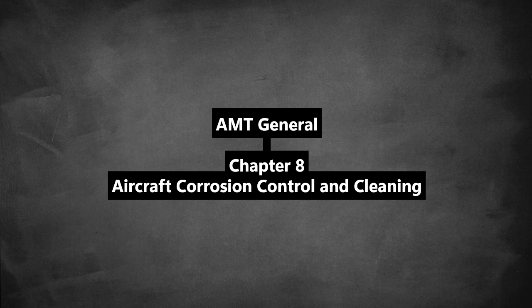Wet wash, dry wash. Wet wash uses water, usually with alkaline or emulsion cleaners sprayed or mopped on, then rinsed off. Good for oil, grease, general dirt. Dry wash uses minimal liquid, applied and wiped off with cloths or mops. Good for light dust or film when liquids aren't desirable. Polishing restores luster and removes light oxidation using various abrasive polishes.